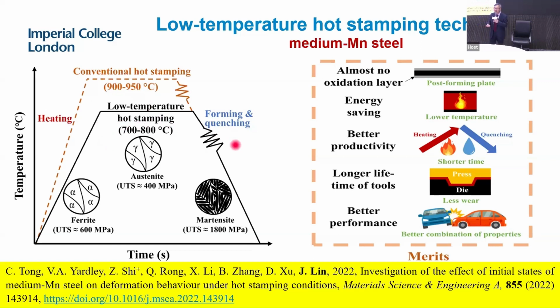Then we tried to develop new alloys which can reduce the austenization temperature by 150 to 200 degrees C, and we call this low temperature hot stamping. We have published some preliminary work, but it has not been used in industry yet. But we have shown the advantages of this. We can avoid the coating and various other issues, and increase the productivity significantly.